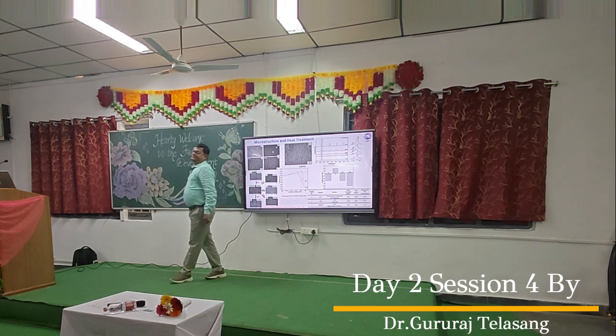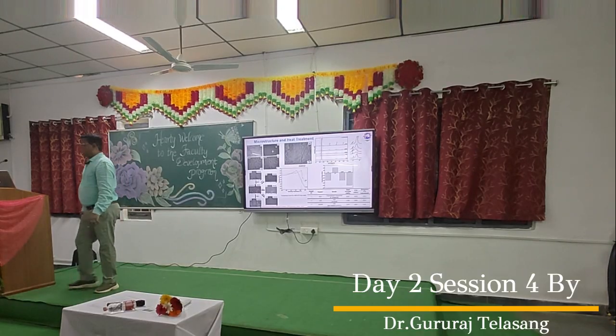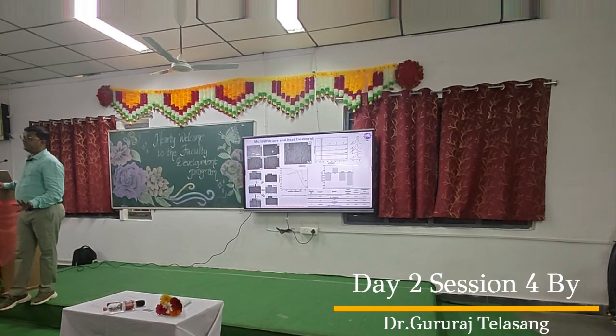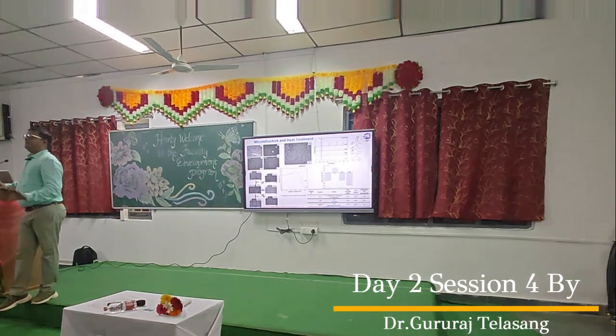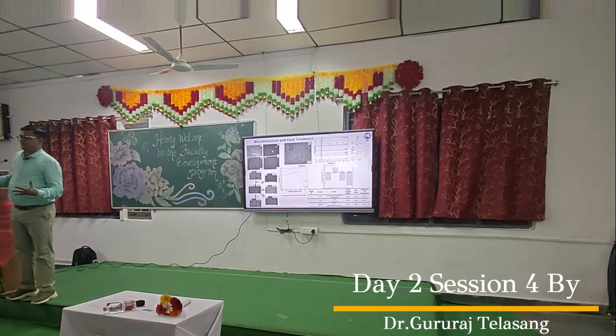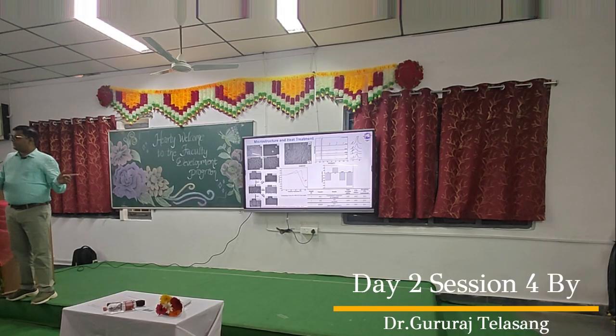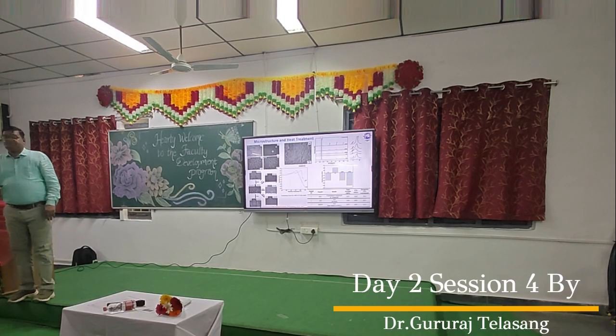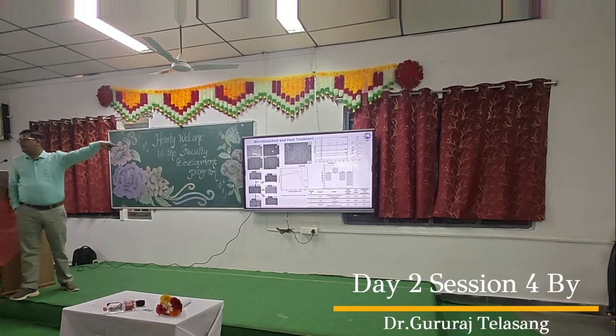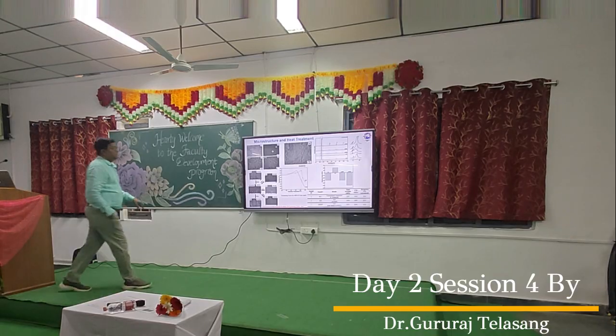This is the advantage we got from rapid solidification. Yes, rapid solidification led to the segregation, dendrites came, a problem, but the microstructure is very refined and very supersaturated. That is called quenching. Quenching followed by tempering. Why do we temper? Quench gives this microstructure. Then you temper, then it will diffuse. Then you will get secondary carbides. But our quenched microstructure is the as-built microstructure because rapid solidification is inbuilt, part of the machine. I don't have to do austenitizing and quenching. I will go directly to tempering, which is the second part. So when I do tempering, I will get very fine carbide and martensite, which has shown this shift.